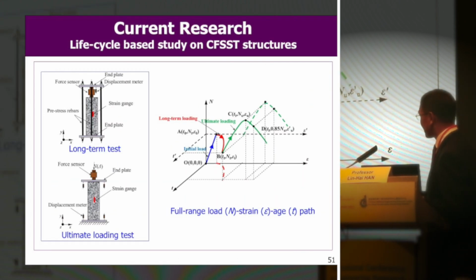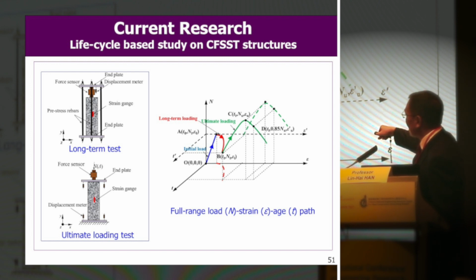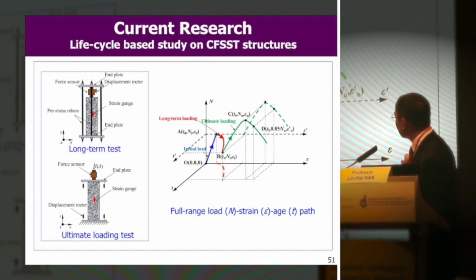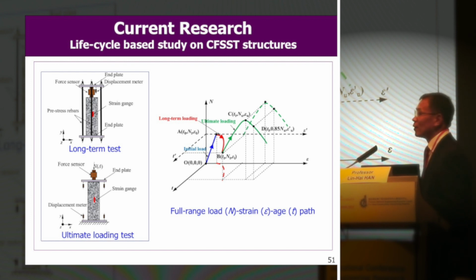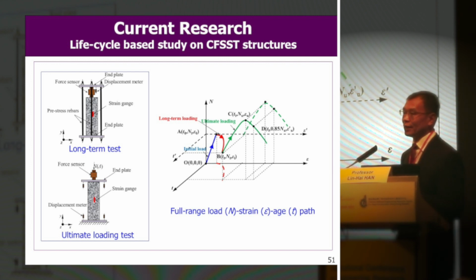Currently we are doing some long-term tests, applying load on the specimen to age it, just like this one. This is a full-range load-strain-age test. This shows the loading, the ageing, and the deformation curve. So we measure the long-term behavior. We apply the design load and keep the load constant to measure shrinkage and creep, and after ageing we apply the load to failure. This is very simple, but can generally reflect the working conditions of concrete filled stainless steel tube under service load and long-term load.